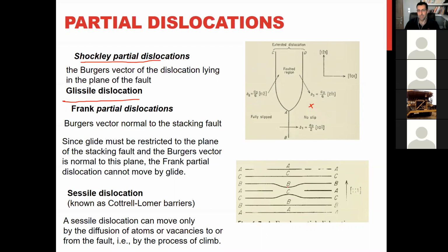The schematic is like this. When you have a dislocation here, and this is the edge dislocation, the Burgers vector is perpendicular to this plane. It means the Burgers vector is not inside of the slip plane. So this partial dislocation cannot move. If you have such a partial dislocation inside of the metal, we call it a sessile dislocation. Another name is Lomer-Cottrell barriers. So not all dislocations can necessarily move. Sometimes a dislocation decomposes into partial dislocations that are sessile dislocations. They cannot move.